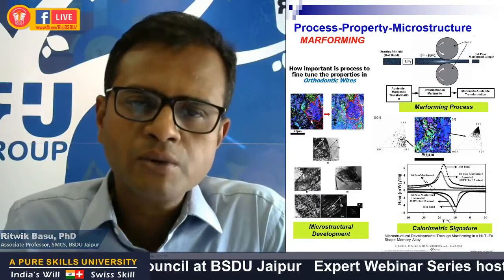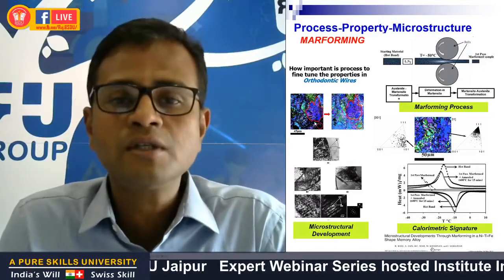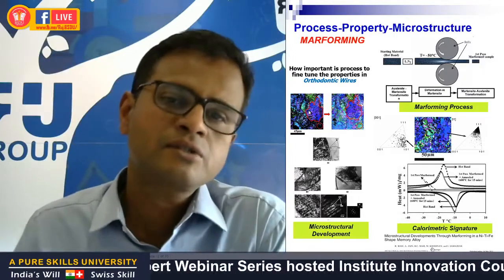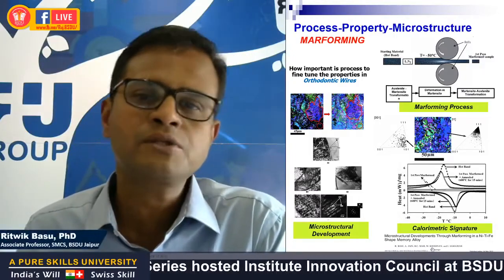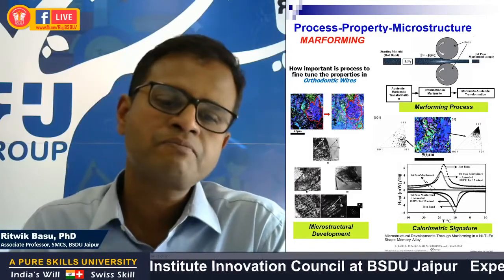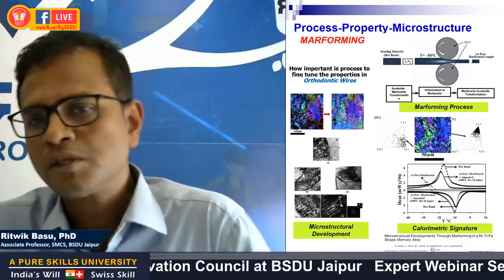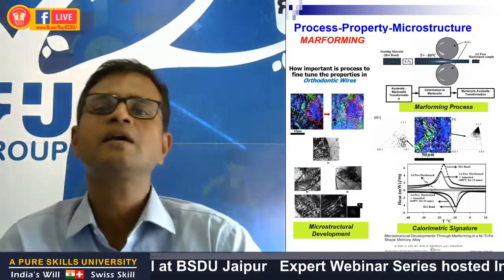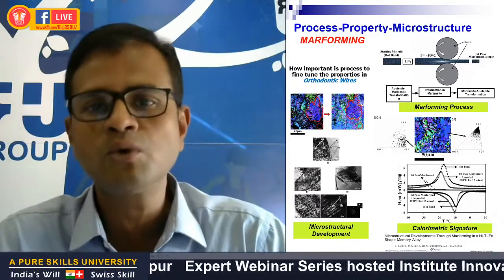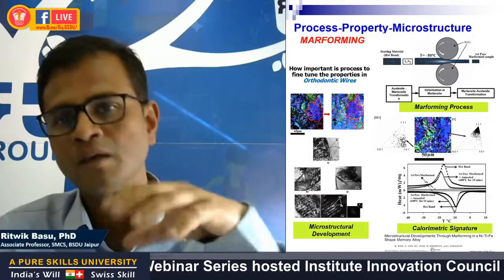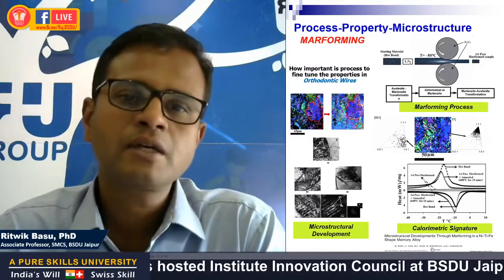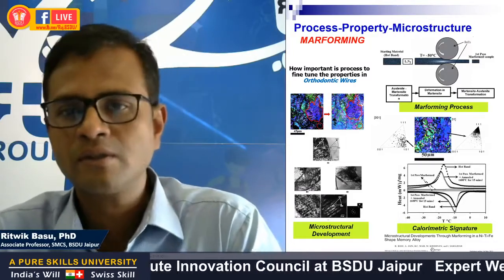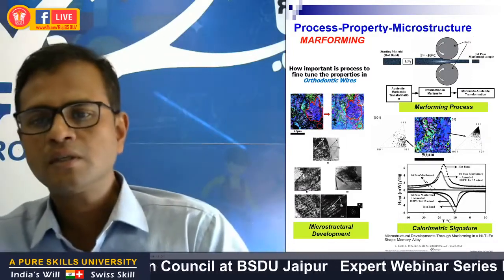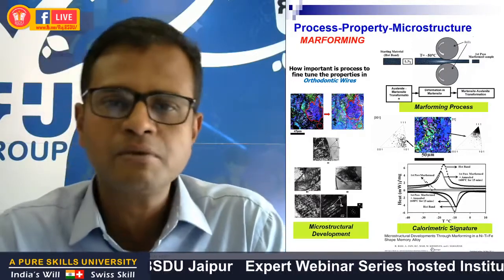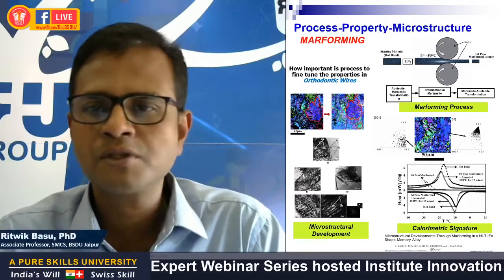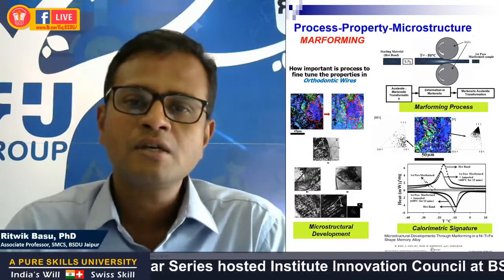So again, marforming without annealing introduces significant strain heterogeneity that is seen through dense dislocation blocks or dense dislocation walls that act as obstacles for the phase boundaries to transform during the forward and the reverse transformation. The ease of phase transformation actually depends on the extent of annealing, the annealing time and temperature. However, there are other factors too, the mode of deformation, the level of deformation, that can also significantly alter the microstructure that in turn can also control the phase transformation characteristics in these materials. So this was work that I carried out during my PhD research, and it was one of the interesting parts of my PhD thesis.